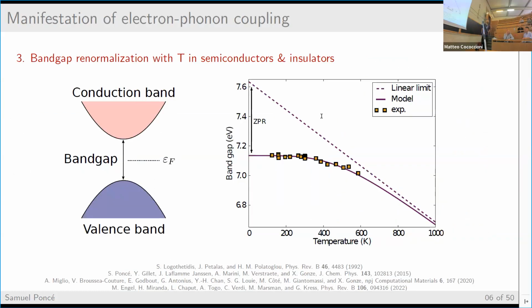Another manifestation of electron-phonon coupling is the band gap renormalization. Again, if you neglect the interaction of electrons and phonons, you have the bare band gap. This is the DFT or GW band gap that you obtain, but in reality, the measured band gap is typically smaller. So you reduce the band gap due to electron-phonon interactions. Notice that even at 0 Kelvin, you have an intrinsic vibration of your atoms. This is the ħω over 2, and this is called the zero-point renormalization.